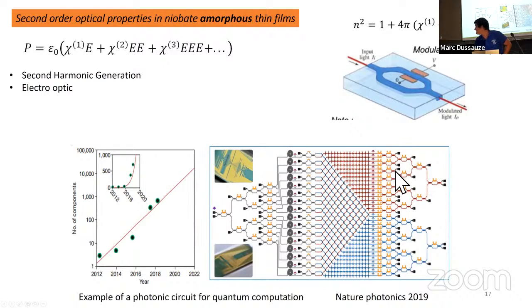But all this part here, where you have these two electrodes, each of them, you see, is a modulator. This cannot be done with glasses. So in this case, you need to combine maybe a glass and then a non-centrosymmetric crystal. That makes everything quite difficult to prepare, in fact. And so there is a lot of need for new materials in such domains. And you can see here the number of optical functions within one optical device like this increases exponentially, like we have seen in the past with electronics.